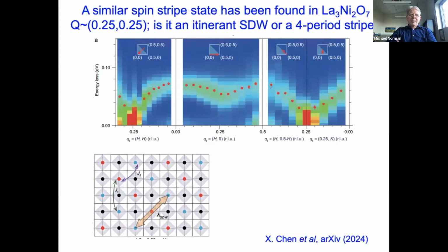The nature of this 4-period stripe state is being debated. You can have something like up, up, down, down. You can have up, down, zero, down, up. You can have all sorts of different kinds of 4-period states. And they've tried to use polarized resonant X-ray scattering to try to realize it. It seems to be this bottom state. As you go along here, blues are up spin, reds are down spin, and the black are non-magnetic states.